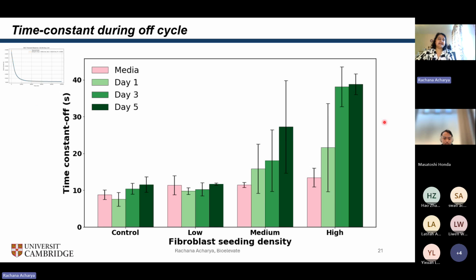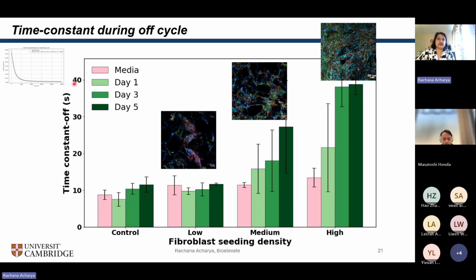Coming to the second metric, which is the time constant during the off cycle. So again, we notice a similar kind of pattern. Just as a reminder, the larger the time constant, the slower the device is in switching off. And this would be because of the cell growth. So we again observe a similar trend where the control and the low seeding density groups do not have much of a change in the time constant, but there is a large increase in this metric for the medium and high densities, which means that it's actually correlating quite well to the growth of cells within the scaffold.